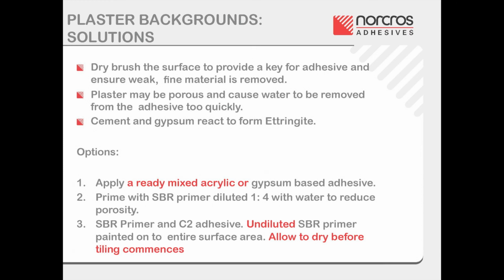Gypsum-based plaster requires special consideration. Ettringite crystals are formed due to a chemical reaction between cement and gypsum-based materials. To avoid this, use an SBR primer and C2 adhesive, or alternatively, a suitable ready-mixed acrylic or gypsum-based adhesive. If using an SBR primer solution to suppress dust and/or reduce the porosity of the plaster, paint on 1 part primer to 4 parts water, covering the whole surface area to be tiled. Allow to dry before tiling commences.